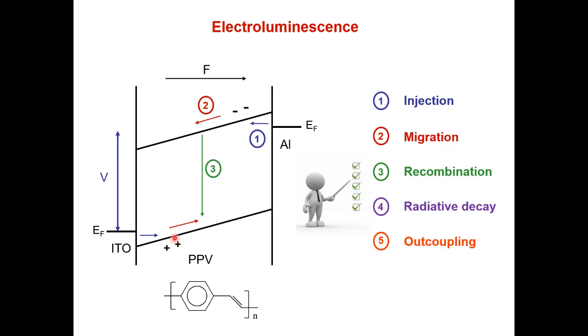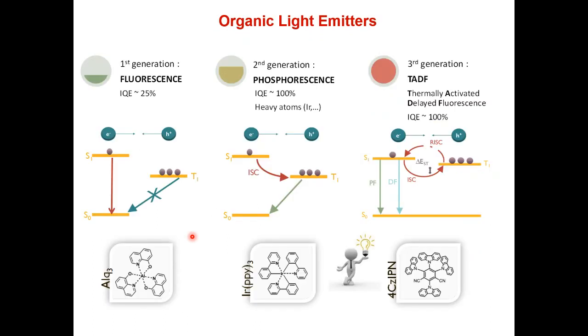And then there is the outcoupling, because you can generate light in the device, but it can be reabsorbed before leaving the device. And this is a major issue, that you need the light going out of the device for the people, for the audience. And so you need to find the right material. This research has been pursued for many, many years. Initially, everybody was using fluorescent material, but there was a big issue. The fact is that when the electron and the hole meet, they don't know anything about the spin they have. You know that an electron is spin up or spin down. And so they can basically recombine into singlet or triplet excitations. In a simple picture, in triplets, you have the two spins parallel. In singlets, they are in opposite directions.